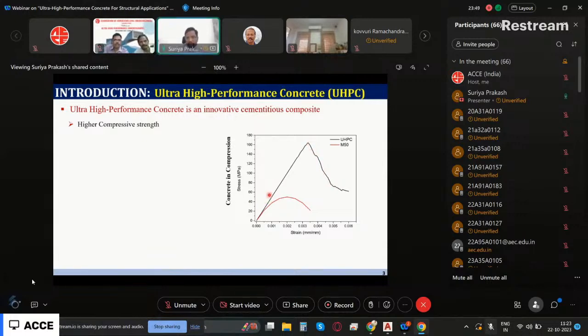So what I am trying to tell here is, this concrete is having 50 megapascal, but this concrete can be designed to have 150, 200, 250, 300 also. So you see here, you get a tremendous increase in your compressive strength. Because of that, I can reduce the size of the structural members. That is a major advantage. In addition to that, you can also see that the stress strain characteristics are going to be different than your normal concrete.